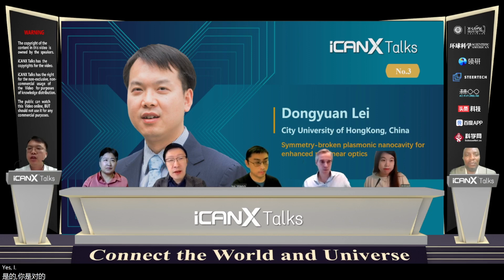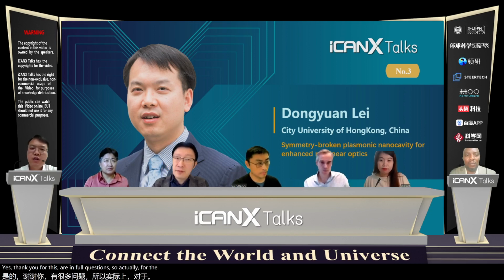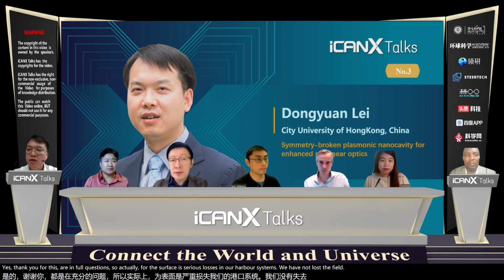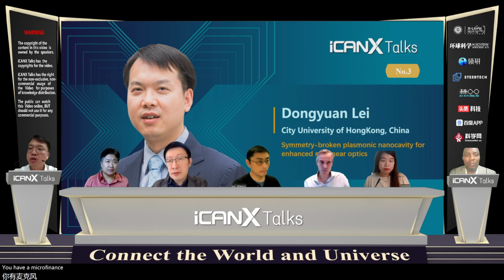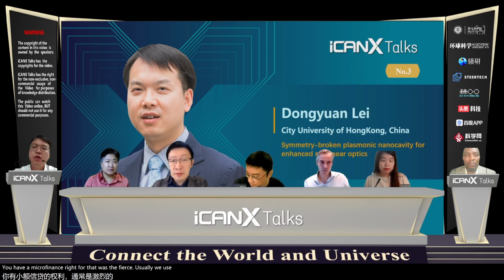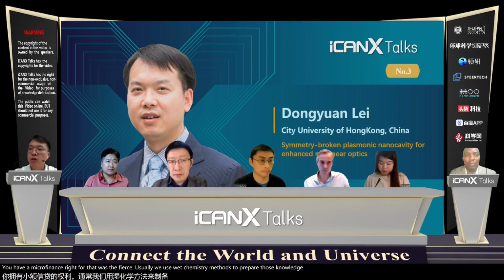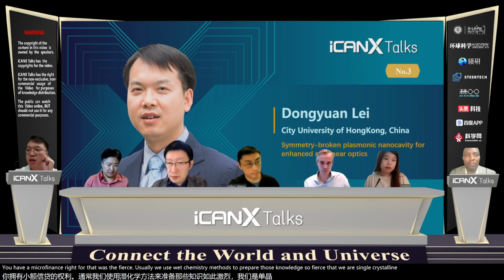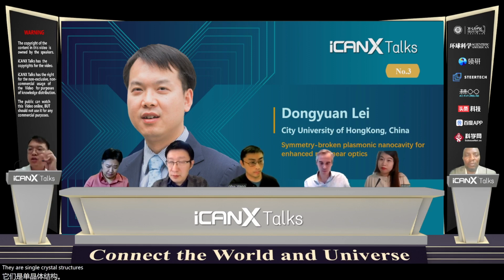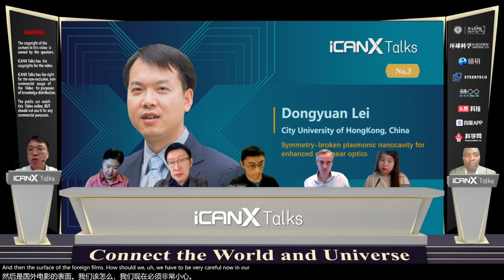Thank you, Nick, for these important questions. For the surfaces here, you notice that in our hybrid systems, we have nanospheres and we have metal films. For nanospheres, we usually use wet chemistry methods to prepare them, so they are single crystal structures and their surfaces are supposed to be very smooth. For the surface of the gold films, we have to be very careful. In our study, we use a so-called template stripping method.